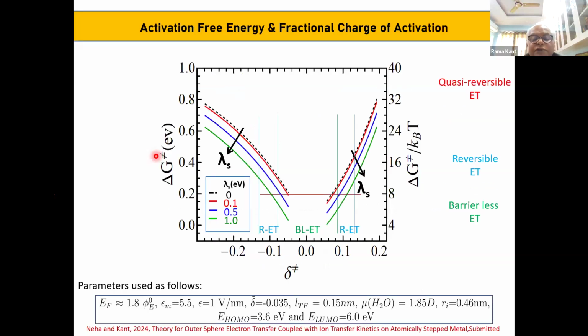So here is the plot of my fractional activation charge and activation energy. There is a central region where the fractional activation charge is near zero. These are the regions where kinetics is barrierless, if you can see here. And similarly, as the activation energy increases, it becomes reversible or Nernstian charge transfer in the electrochemistry context. Up to say 8 kBT energy, it is barrierless, up to 8 or 10. Then up to say 15, 16, you have reversible charge transfer. Above that, you have quasi-reversible charge transfer. And as we increase the solvent reorganization energy lambda, this activation energy decreases, shown for 3 different reorganization energies. And these are various parameters.